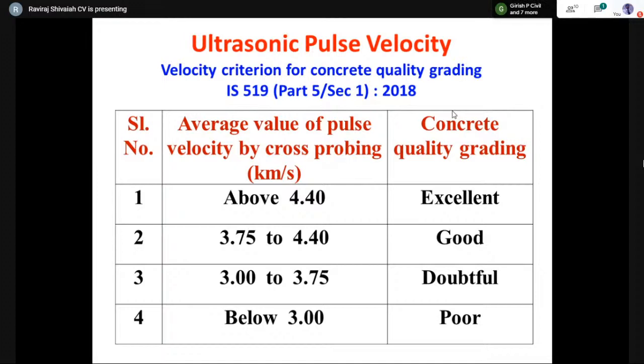3.75 to 4.4 kilometers per second, the concrete quality is good. 3 to 3.75 is doubtful, in which case you have to do some further investigations on the concrete. Below 3, it is poor. So this is what we would ultimately be looking at once we do the test regarding the velocities, and then we need to understand whether the quality is good or whether we really need to do more tests to check the real problem in the concrete and then think of remedial measures.